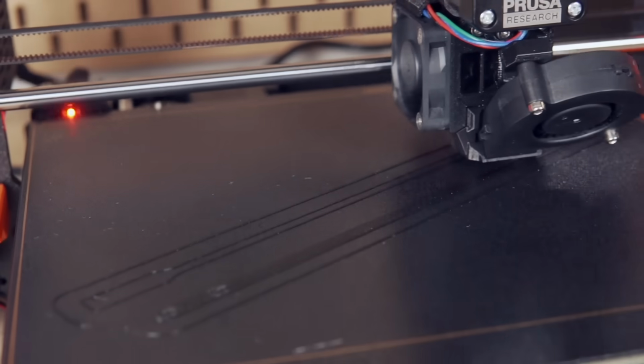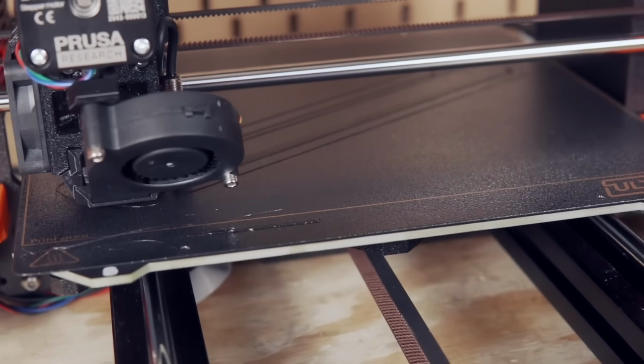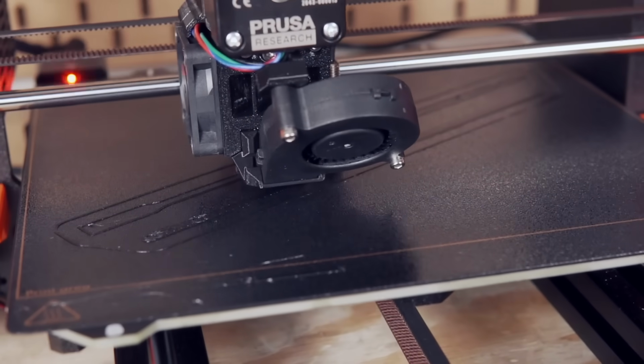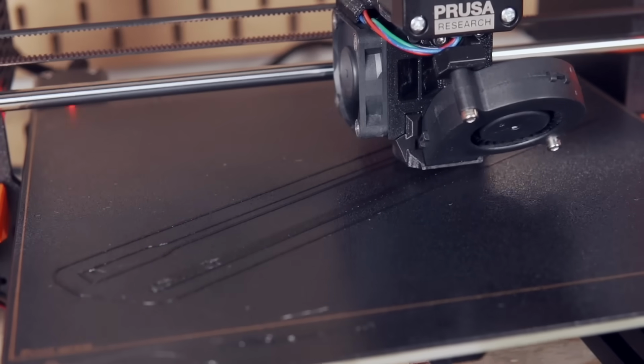So on glass, I typically use a bit of glue stick. I have powder coated PEI sheets on most of my printers that I'm doing a lot of printing with because it's just my go-to. But again, if you've got a standard build plate, or kind of what the Creality machines come with, a lot of them is a knockoff BuildTak or smooth PEI, be sure to put something down like glue stick, otherwise you will run the risk of damaging your bed surface. Good news is, unlike ABS, you do not need to have an enclosure to print with PETG, and I would say that 90% or more of my PETG printing over the years has been done on open format machines.